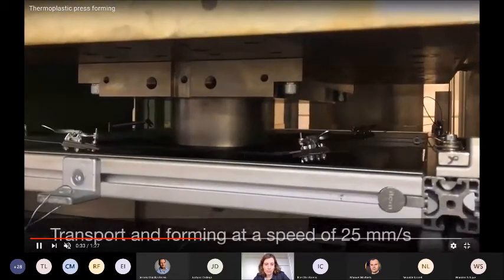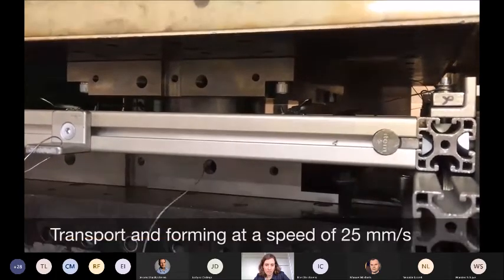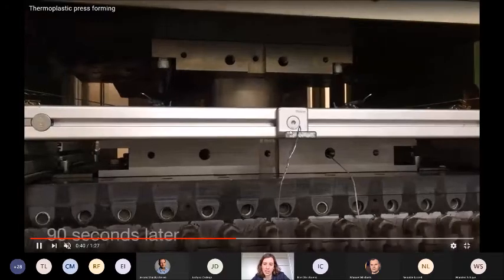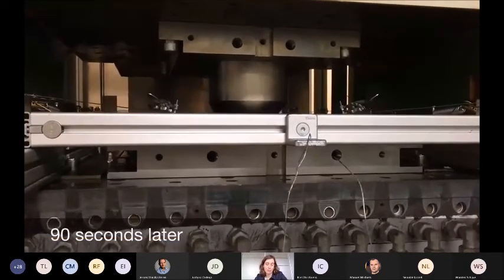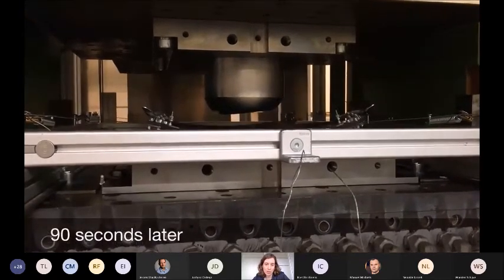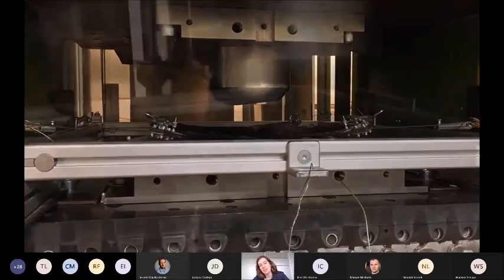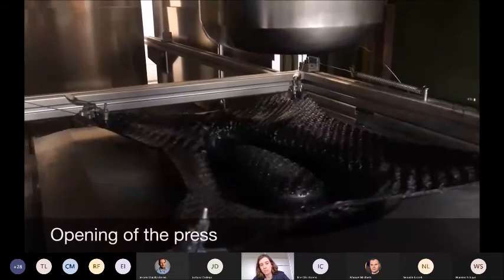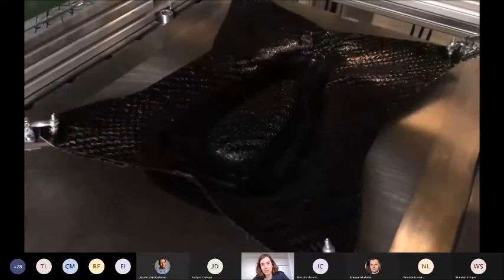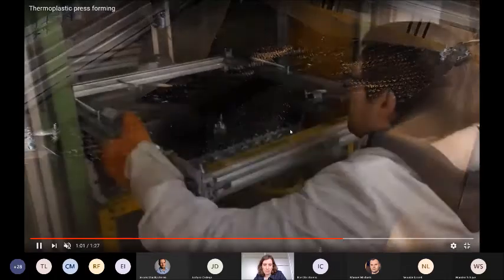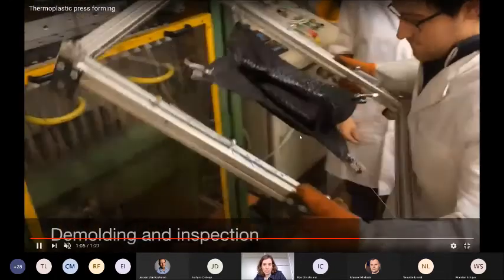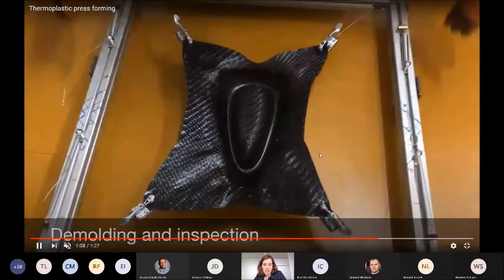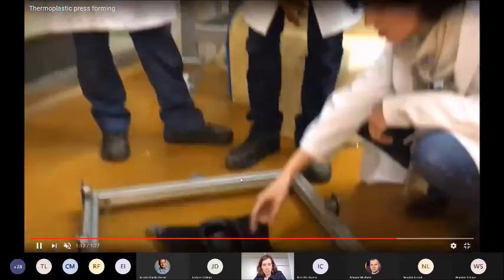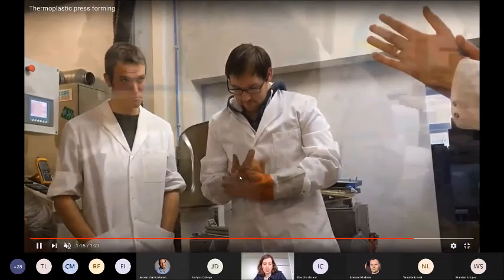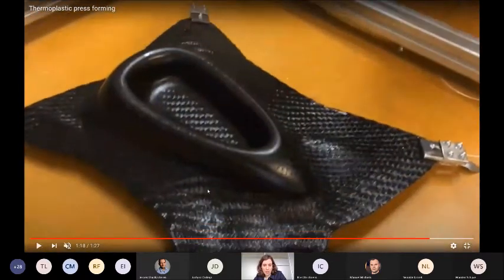There's a transportation to the press, and then the press is closed. And since the material is melted completely, it can form quite easily into the shape that we want. And the cycle time of this kind of process is around 2 minutes, 1 minute. So it's quite a fast process. And then we demold. It is possible to make these kind of products net shape. You can see here in the video, this was not yet the case. So basically what we would need to do is to trim the product afterwards.